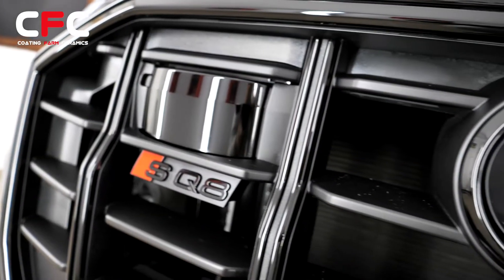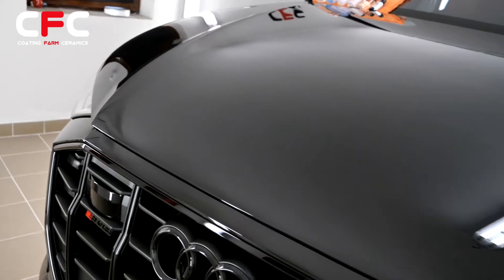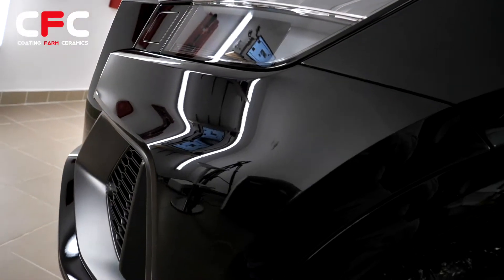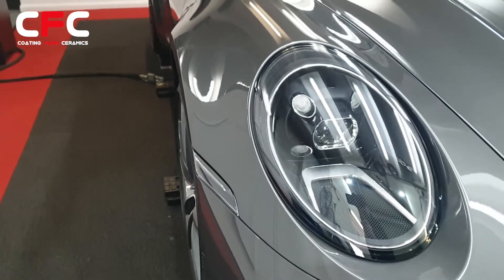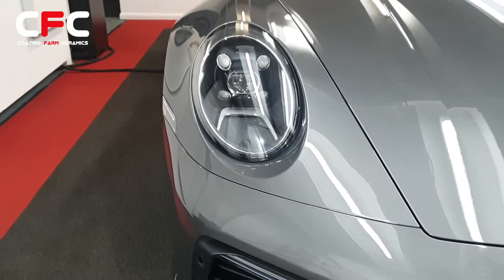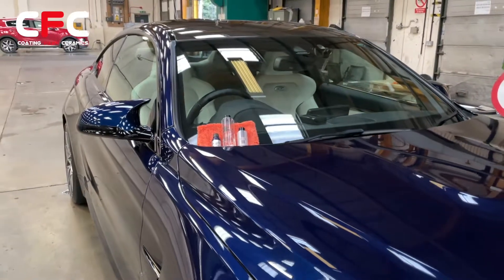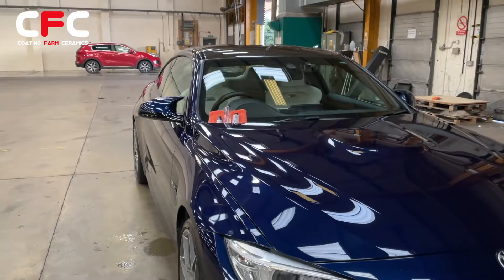So how is this testing done? Basically, SGS tests the scratch resistance of a ceramic coating using the Pencil Hardness Scale test. This range covers from 2H, which is the softest, to 10H, which is the hardest. CFC's Alpha Coat has been tested by SGS in this manner with a Mitsubishi 10H Uni Pencil. The test consists of the pencil having a 1kg weight applied to it and pushed along the ceramic coated surface at 30mm a minute.